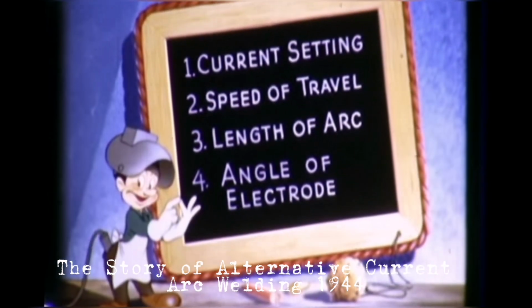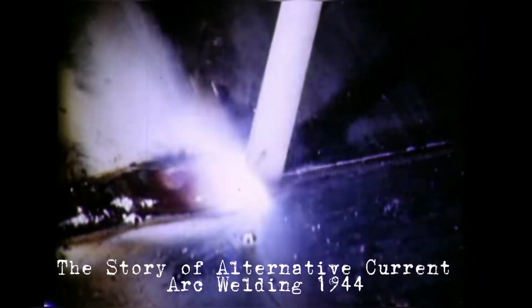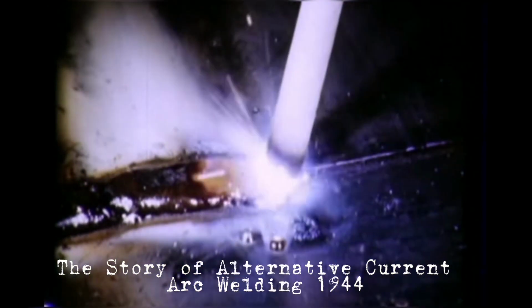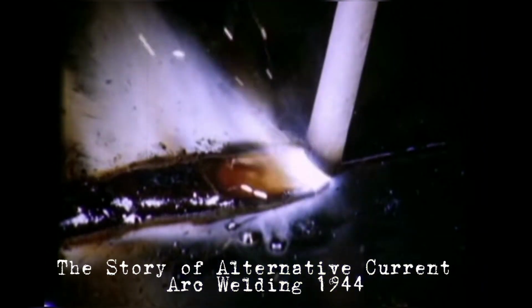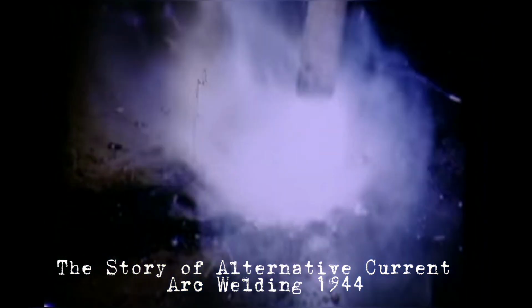The third main factor is the length of arc. Too short an arc is hard to maintain, and the weld is likely to trap slag and gases. If the arc is too long, it is erratic and spatter is excessive.